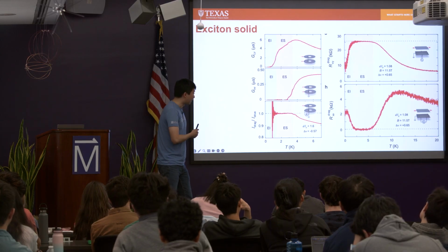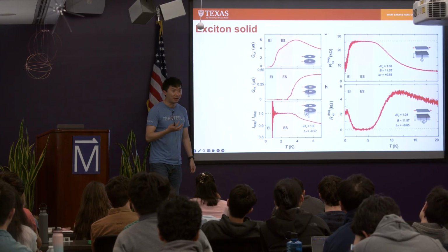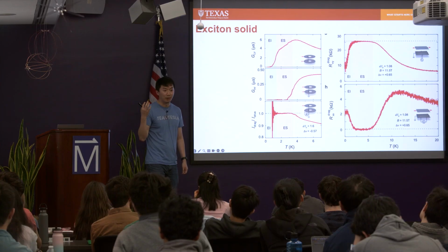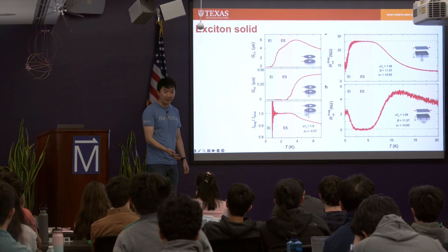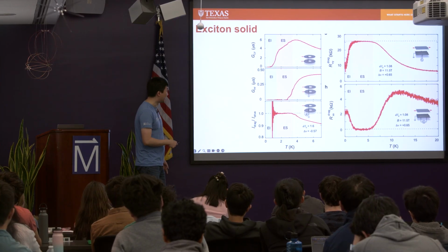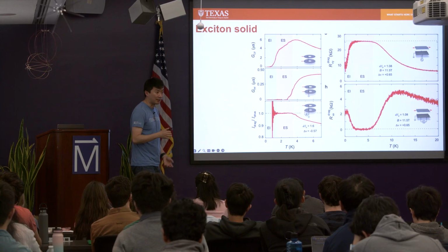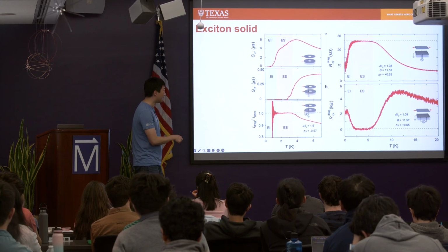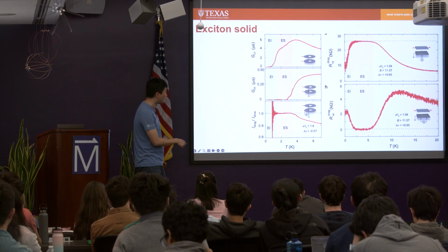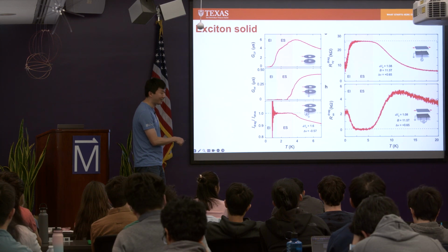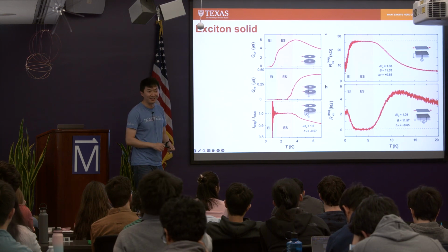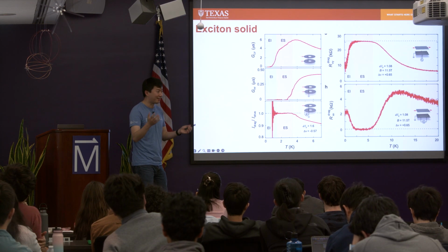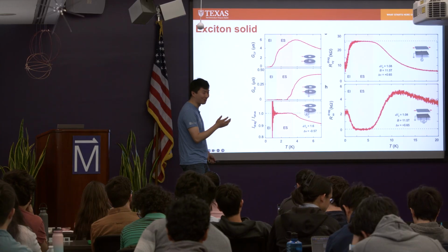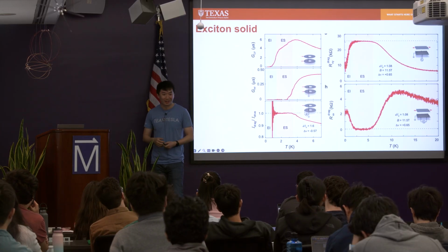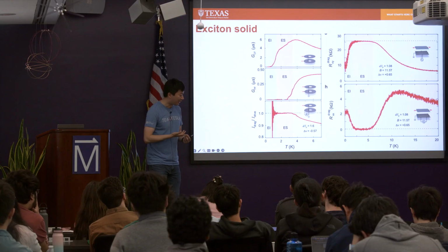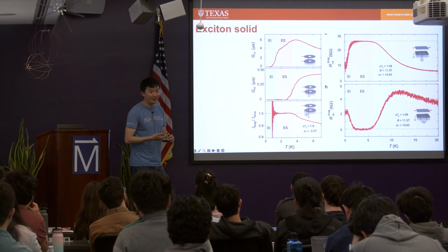So this actually raises a lot of really interesting questions. When we talk about bosonic condensate, we always assume that's the low temperature ground state, right? And this shows that there is a different low temperature ground state under the right condition, right? When you cool down in temperature, you could hit a superfluid first, and then you hit another state that has a lower entropy than the superfluid state. So it's a question that at that time we asked a lot of theorists. How can an insulator show lower entropy than the superfluid?